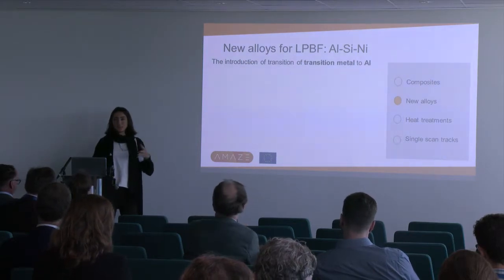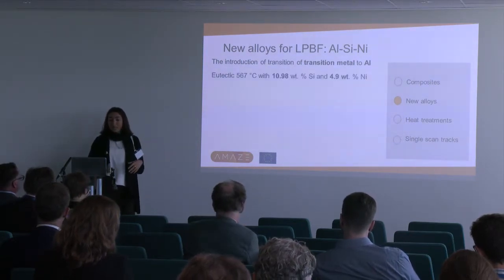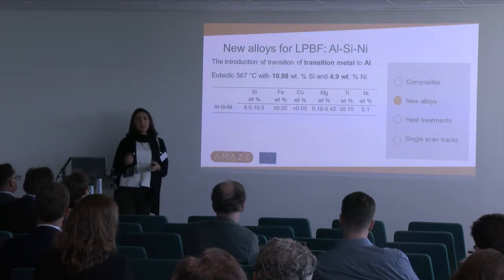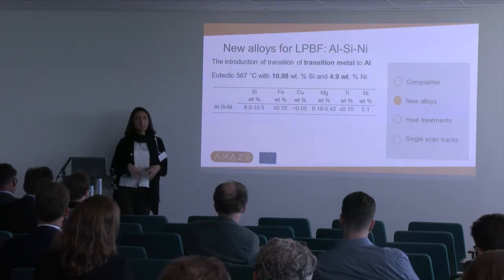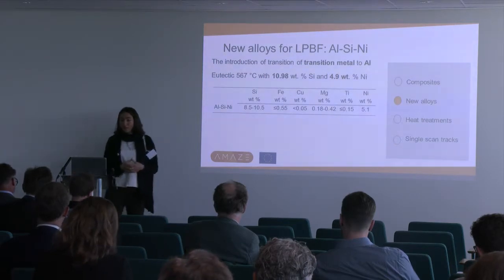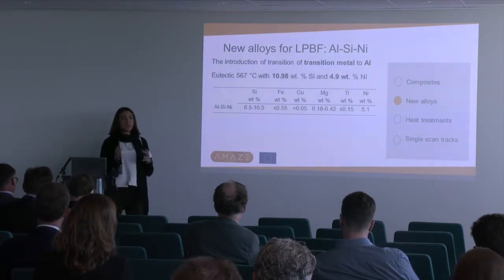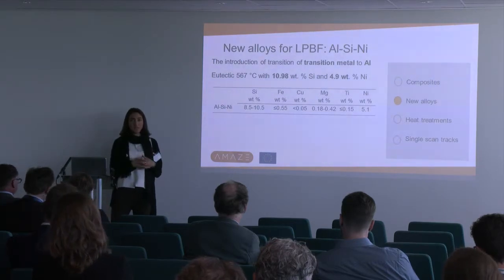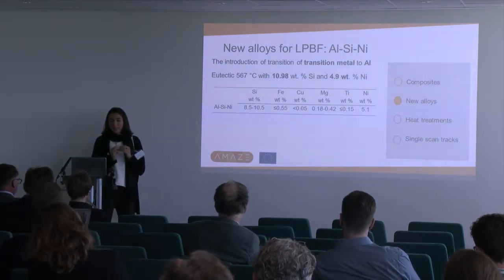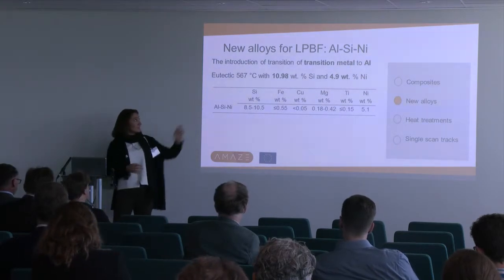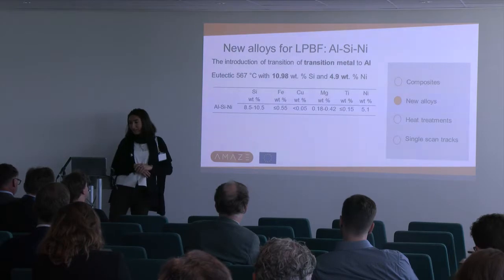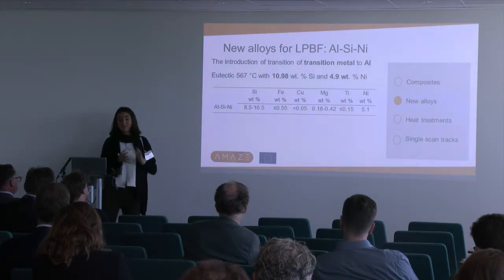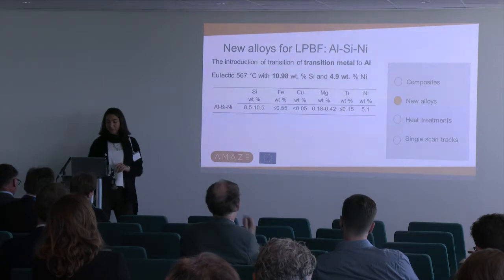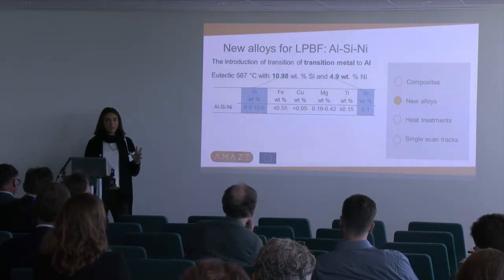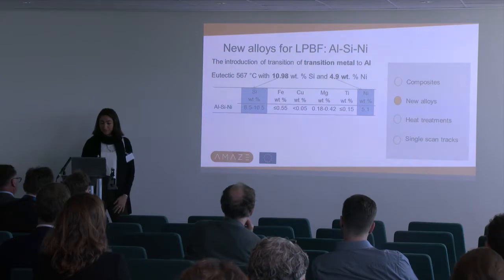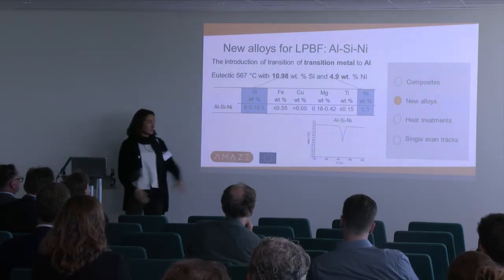So we started from aluminum silicon 10 magnesium alloy. And from the literature, it's well known that the introduction of transition metal to fast cool aluminum can increase the mechanical properties of the aluminum. As we also wanted to have a small solidification range, we wanted to be near to the eutectic. So we have a eutectic between aluminum silicon and nickel, which has 10% of silicon and 5% of nickel. So we chose a composition which was close to that eutectic.